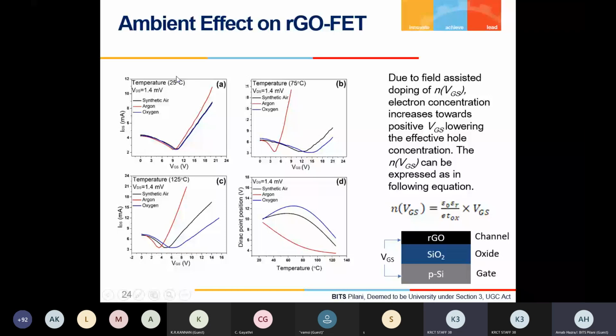But when the temperature is 75 degrees centigrade, then the surface reaction possibility was increased significantly. And now there is a significant difference in different ambient. In argon ambient, the oxygen free ambient, the hole concentration was initially low. So we achieve the Dirac point before the others. Then after achieving the Dirac point, it starts to increase rapidly when the electron is the majority carrier. Now this is the synthetic air and the oxygen. They are also following the same trend. At 125 degrees centigrade, they are also showing some ambient related variation, keeping the ID-VGS same.